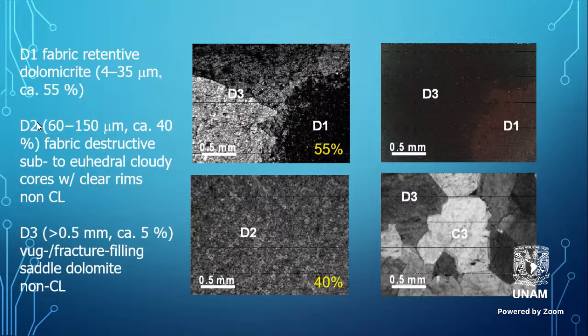The second type of dolomite there I call D2, and it has crystal size between 60 to 150 microns, calibrated at about 40% of the total content of the dolomite in the core, and consists of subhedral to euhedral crystals. They have cloudy cores and clear rims, and in fact they are fabric destructive, so you cannot trace the fabric in that type of dolomite.